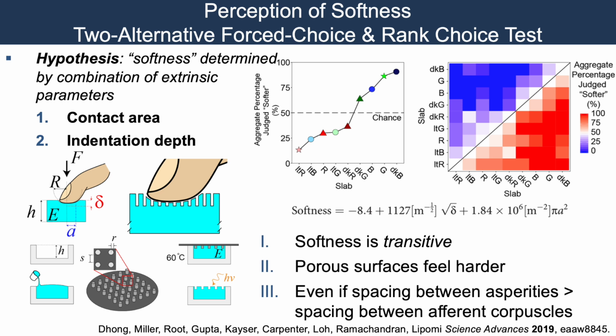So you can reduce the real contact area by putting these little air gaps in between. It's kind of equivalent to a rough or porous surface. And then you can influence the indentation depth by making these surfaces very thin.